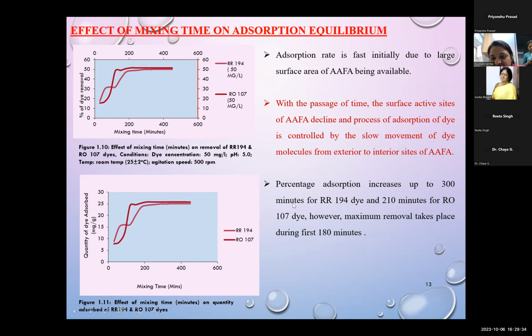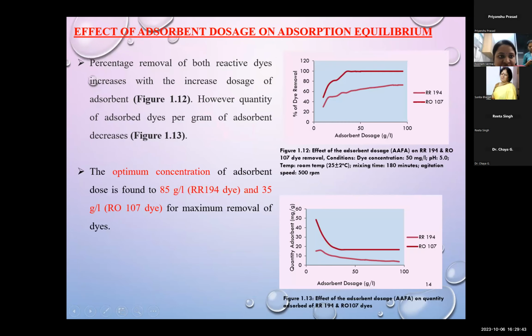Percentage adsorption increases up to 300 minutes for reactive red dye and up to 210 minutes for reactive orange dye. However, maximum removal takes place during the first 180 minutes.